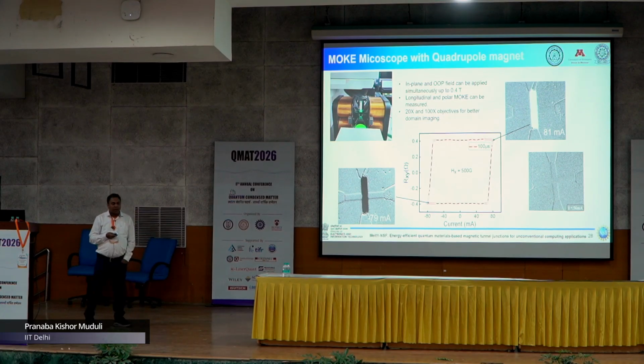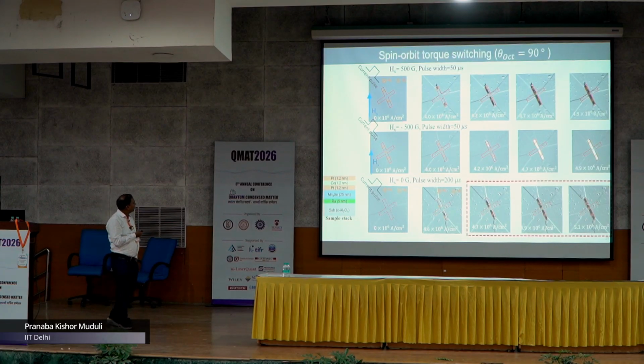And here is the result. This is a Hall bar device, and here the current is passed like that, and this current is increasing here. This is an in-plane field, and this is the pulse width. As you can see, it is switching slowly, and it is completely switched. And here, if you change the field direction, you switch the other way, which is consistent with the SOT mechanism. Also, you can get the switching even at zero field. So field-free switching at zero field we are also able to get.